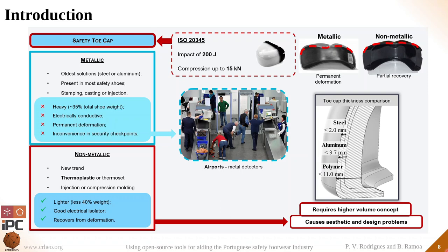Comparing both solutions, metallic toe caps tend to be heavier and can represent up to 35% of the total shoe weight. It conducts electricity, which increases the risk of electrical shock, and it can cause inconvenience in security checkpoints due to metal detectors. And after a critical mechanical solicitation, the toe cap deformation can be permanent, which makes removal of the user's feet difficult. On the other hand, non-metallic solutions can be up to 40% lighter, and they are good insulators and are capable of recovering from deformation. But to have a comparable mechanical performance to metallic solutions, the non-metallic toe caps require a higher volume concept, which results in a bulkier shoe, which causes aesthetic and design problems to the safety footwear industry.